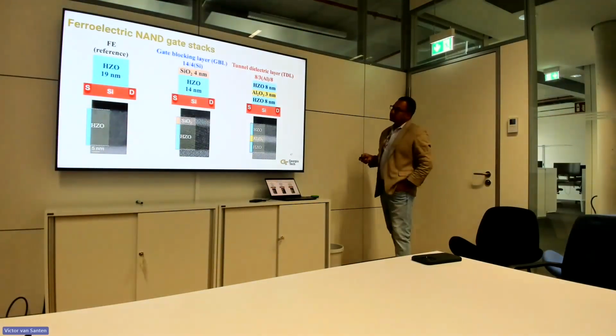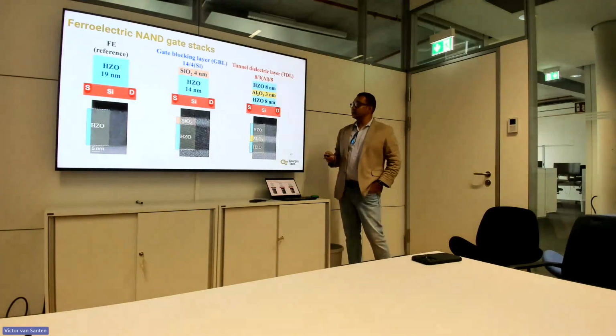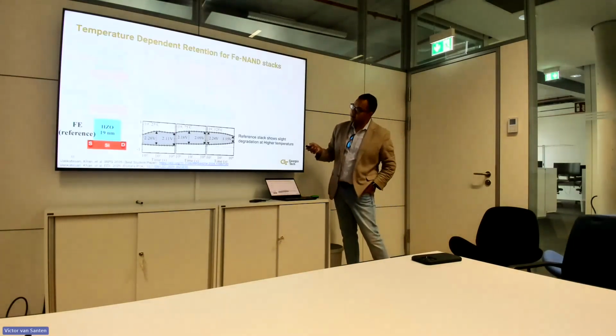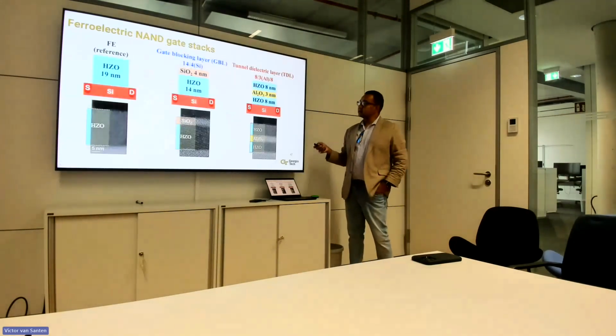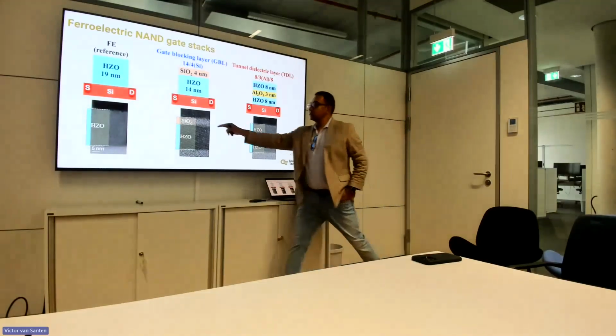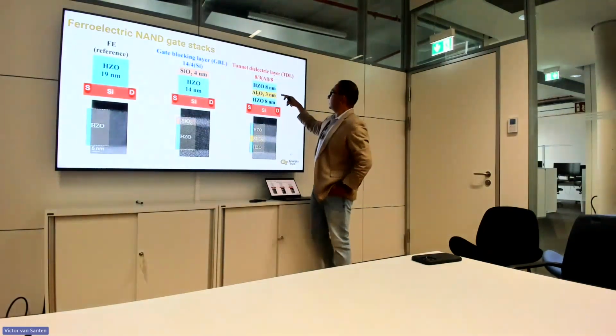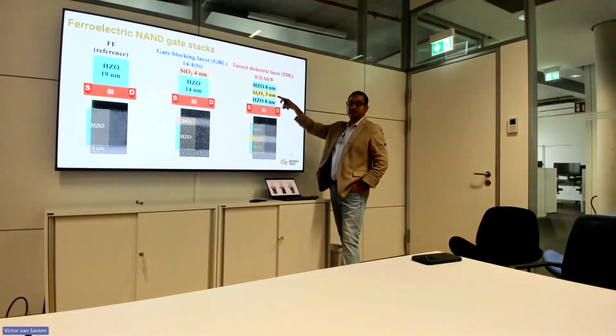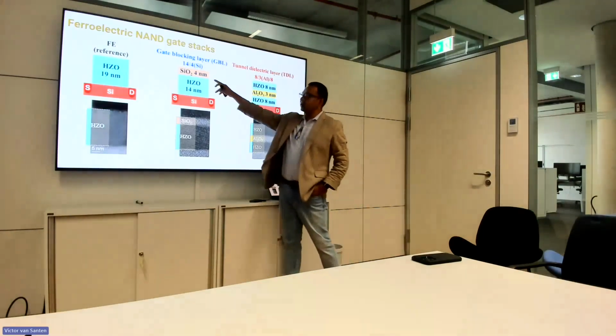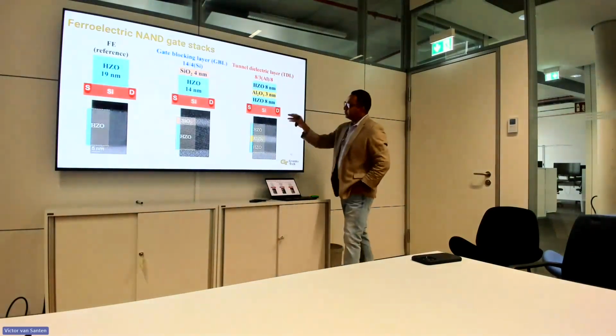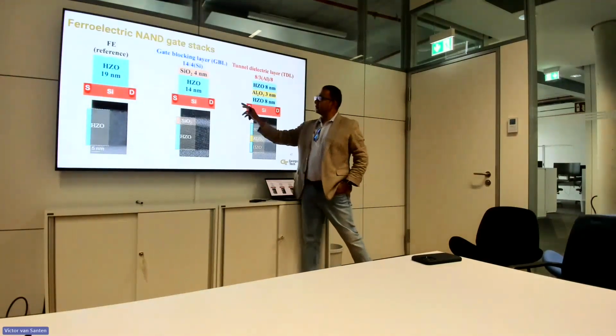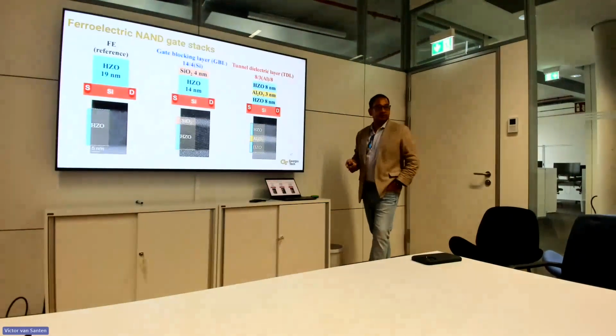Okay, so the first thing that we looked at was retention. I'll quickly go to the next slide. We took 3 different devices. One is the pure ferroelectric, then one with aluminum oxide in the middle, and then one with silicon dioxide on the top. In both cases, the main thing is that both of these devices show a very large memory window.